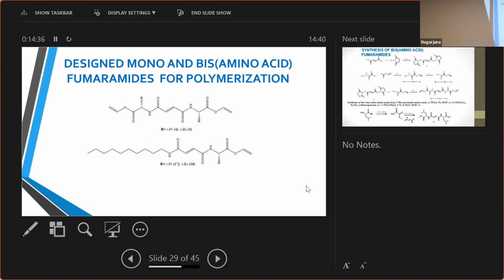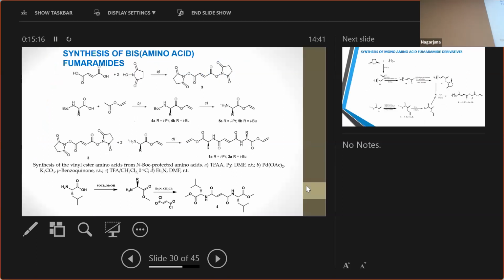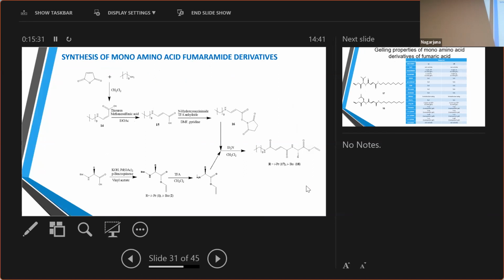And from this first compound, we do some modification, and on fumaric acid we put a vinyl group, and design molecules that we call bis amino acid fumaramides. Also here is an example of mono amino acid fumaramides with a long chain. The synthesis is done in a few reaction steps to the final compounds, in a moderate yield of about 50 to 60%. Also, here is a scheme of synthesis of mono amino acid fumaramide derivatives.